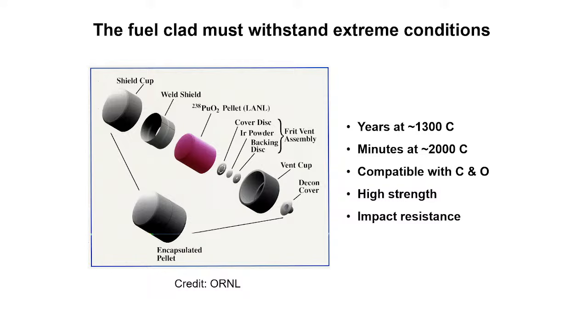This is the plutonium oxide fuel pellet, which at steady state is sitting around 1300, 1350 degrees Celsius. And these are the two cups that are made with iridium metal. The iridium metal is clamped around the plutonium, and then you weld it shut. There's a weld shield that goes in here, because when you weld it, you don't want to accidentally blow up the plutonium oxide. And when you put all this together, this is what each pellet looks like.